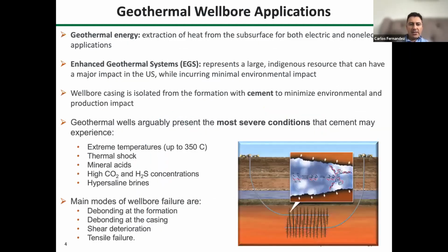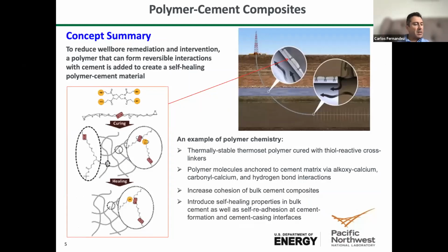I think everybody talked about this, particularly in the last two talks: the wellbore failure modes, the bonding to formation, the bonding to casing, the shear deterioration that we were just listening to questions about, and the tensile failure, the radial fractures generated in confined environments. This is due to extreme temperatures, up to 350 Celsius, while in EGS it can be 450 Celsius, in some cases even 500 Celsius for super hot EGS. And the thermal shock and chemically harsh environments can introduce any of these failure modes to the cement in the wellbore.